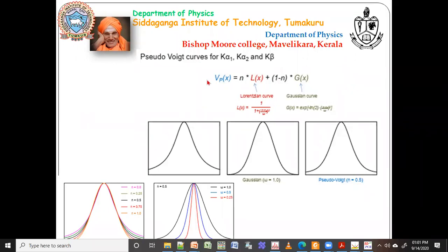Okay, sir. Sir, there is a question from Swadi Shaktivel: what is the difference between the structural model and profile matching with a constant scale factor? The structural model is your Rietveld refinement. When you want to do Rietveld refinement, you have to give the atomic positions of your elements. But in profile matching, we are not fitting atomic positions. We are just trying to fit the contribution of your instrument. We are trying to find the a, b, c and also the symmetry, and also fit the instrument.